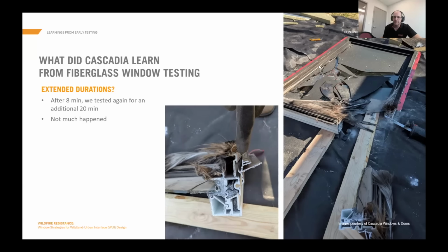So you can see the rest of the frame is just as it is. But in this location, we observed that the outer surface of resin on fiberglass is combustible, so it catches fire and burns away. It burns away that surface of resin on the outside that in the natural product is there to accept paint. And then what's revealed underneath is a layer of glass that cannot burn, and it acts almost like a fire blanket locally to what's behind it. Heat transfers through, but not fire. So enough heat transferred through that it melted the foam insulation that was in these cavities. But you can tell that the heat didn't penetrate too far into this multi-chambered frame. The second chamber got hot enough to make the foam recede a bit, but not melt. And then inboard of that, it's totally fine.